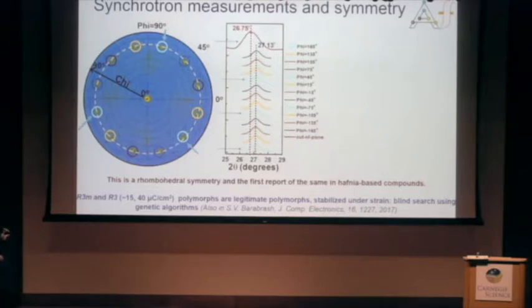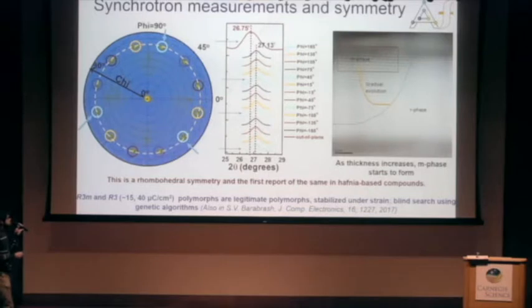And the polarizations of the more stable phases are like 15 microcoulomb per centimeter square, actually less than what we measure experimentally. So this is one of the cases where theory is predicting lower numbers than what we are seeing experimentally. Okay, so as you keep increasing the thickness, this picture shows a gradual evolution to the M phase.